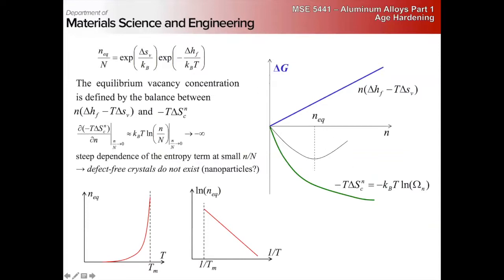Even with the vibrational term, it still looks a heck of a lot like it did without. That vibrational term ends up being small. But it's natural to ask whether or not it's important. It's just a correction on this linear term. It's just going to slightly reduce the slope. So if the slope is reduced, you're going to have a slightly higher number of vacancies if you include the vibrational term. So it's kind of an important concept, right?